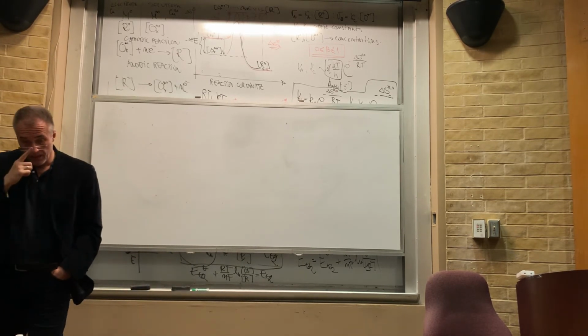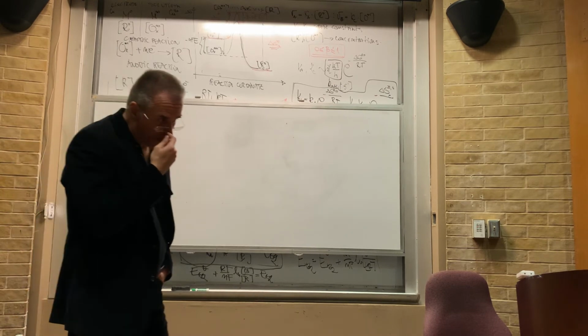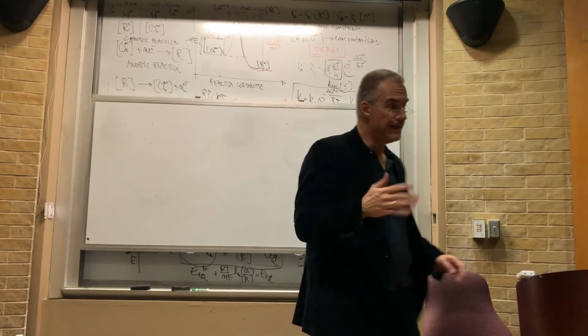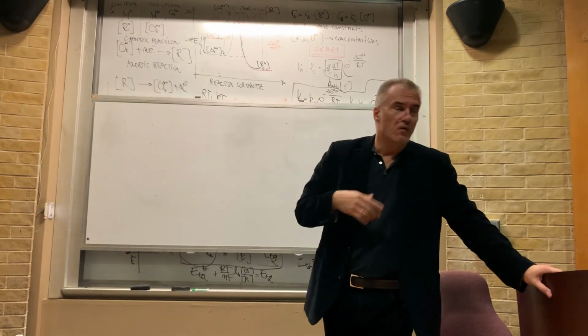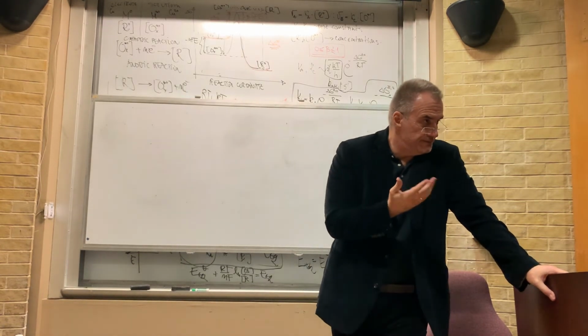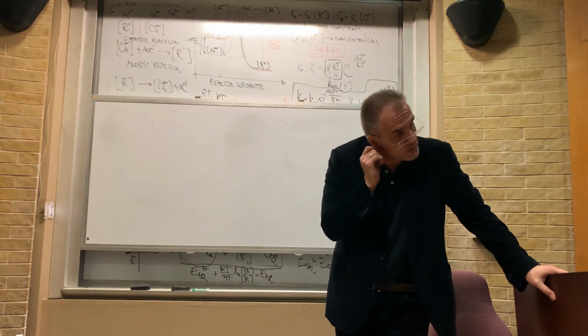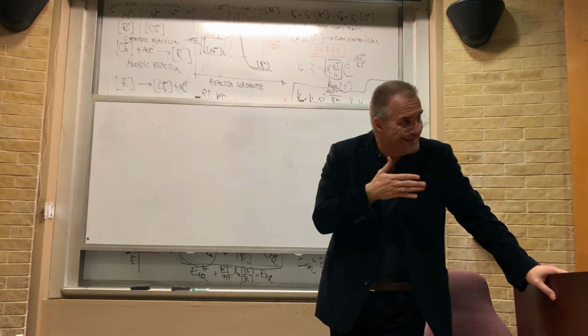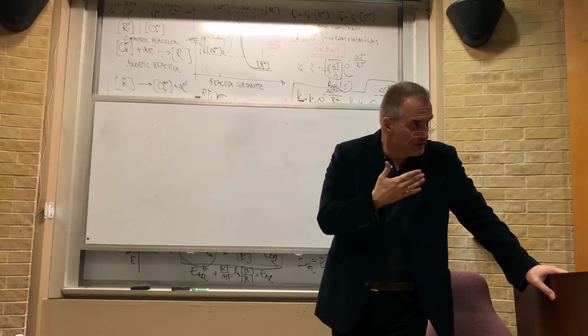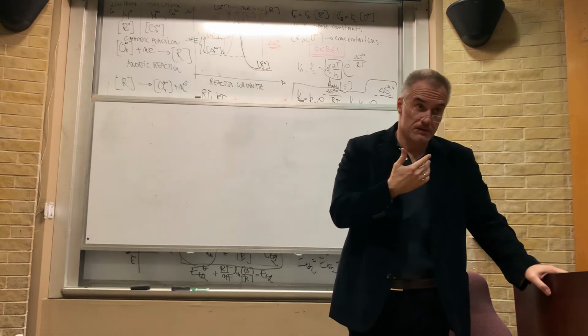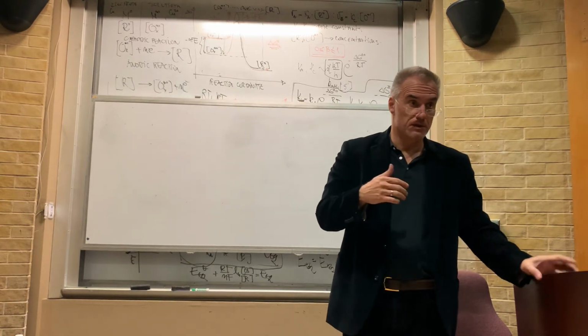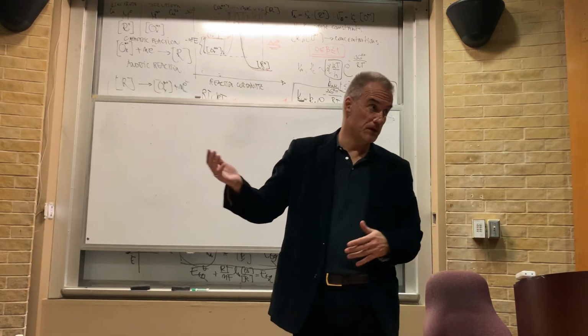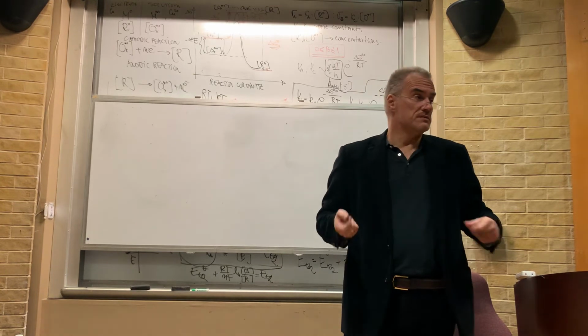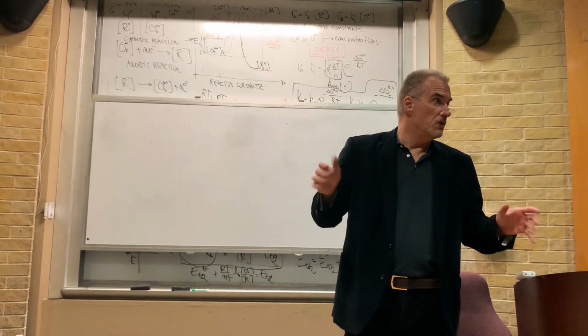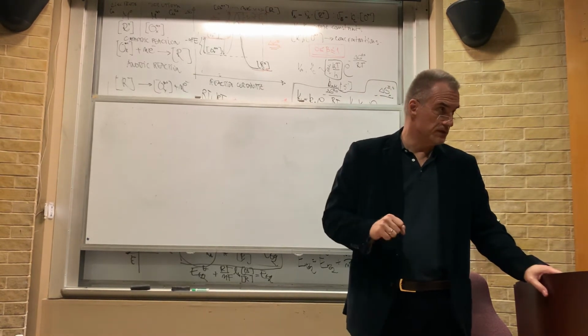Okay. Now one thing that we do in electrochemistry, instead of measuring net rate, what we do measure is the current. That's how the instrumentation works. We measure the current. The net rate between cathodic and anodic reaction is whether anodic is higher versus cathodic, and so you measure anodic, which is positive, or cathodic, which is negative current. You always measure some current as a function of the potential applied across the interface, right?